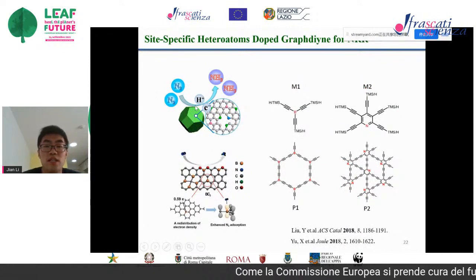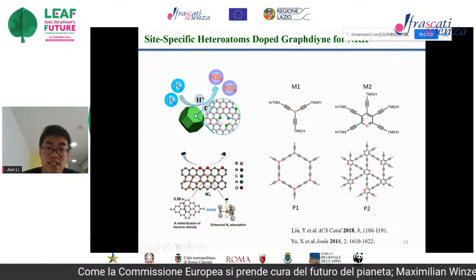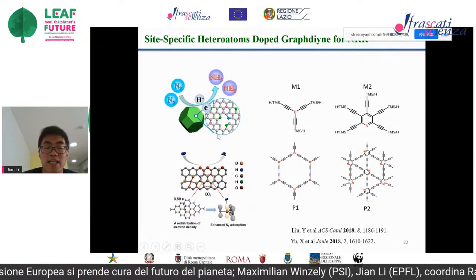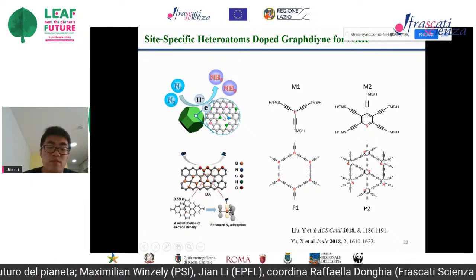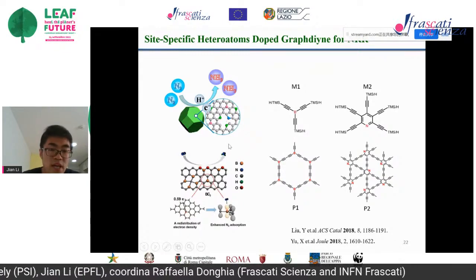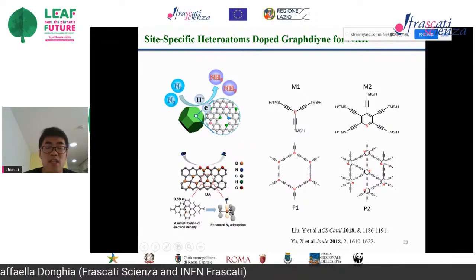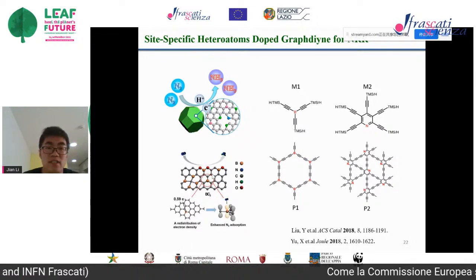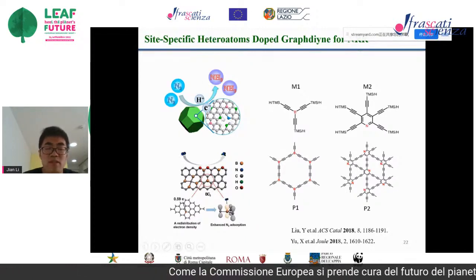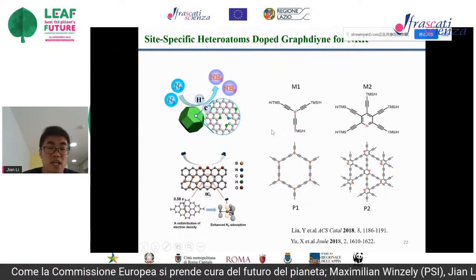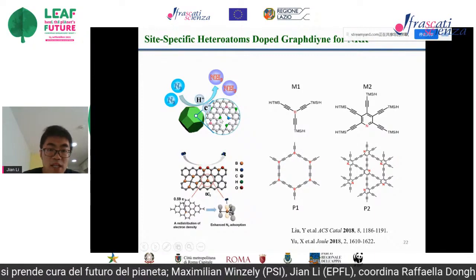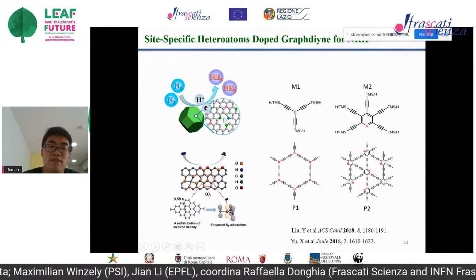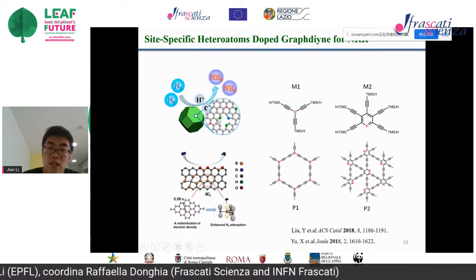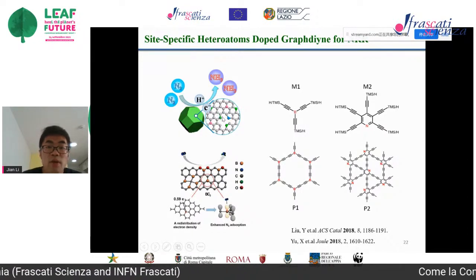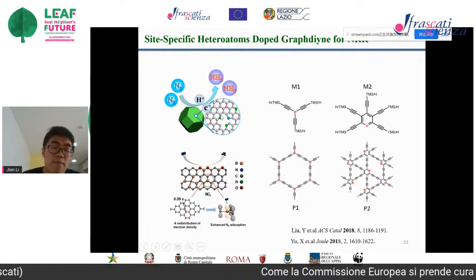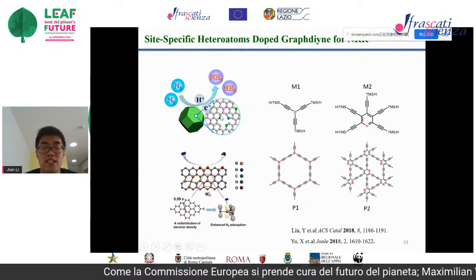So if we want to design the catalyst, the catalytic site is very important. So we should design the catalytic site. Previous studies have proved that the pyridine nitrogen and the boron-carbon-3 structure are very efficient active sites for nitrogen reduction. But previous methods cannot synthesize these sites specifically. They can synthesize a lot of nitrogen, you can see this is nitrogen, but not all of the nitrogen is pyridine nitrogen. Only this one is not pyridine nitrogen. So if we can control the active site and only synthesize pyridine nitrogen, we can largely improve the activity.